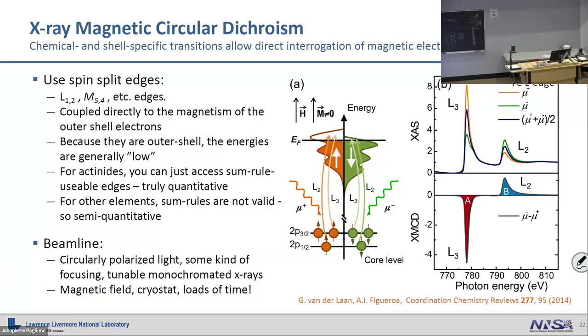If you do this at the magnetic edge, so let's say for iron, you need to do this at the 3D edge. The 3D electrons are the ones that are magnetic. So you have to couple to that. That's only at a couple hundred electron volts, right? The 3Ds are right up by the Fermi level.